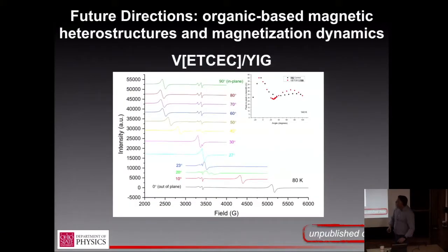And I think maybe the last thing I'll show you, and this is very poorly understood, is that rather than depositing on sapphire, we can deposit on YIG. And then in principle, we've made a bilayer of the two narrowest line width, sort of best ferromagnets that we can. For reasons of attempted cleverness by the advisor, this is VETCEC rather than V[TCNE]x, which didn't end up working out. But the thing I want to point out is that this material is maybe not of the highest quality. So this is the line corresponding to the organic, and this is the YIG line, which is tuning through as we vary the angle. And so basically we can use the shape anisotropy and magnetocrystalline anisotropy of the YIG to tune its resonance frequency through the resonance frequency of the organic.